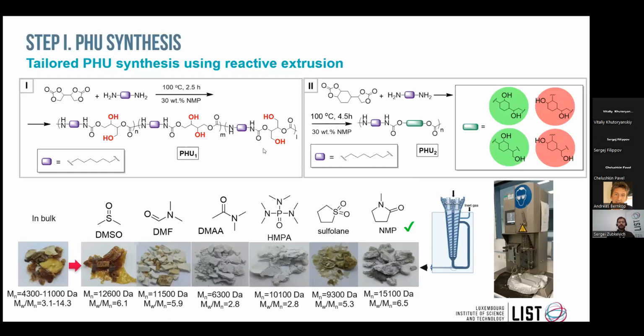We have synthesized two polymers, one with an aliphatic, less rigid chain and one with a cycloaliphatic, more rigid chain, that have adjacent OH groups in the polymer backbone. For the second one, derived from vinylcyclohexene dicarbonate, we have different isomers as for the first one, but none of them favor further modification, which will result in a lower degree of modification for this type of polymer.